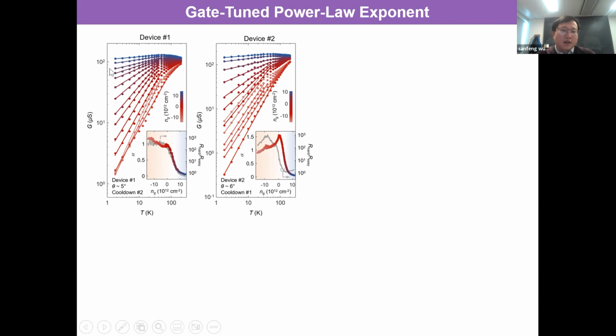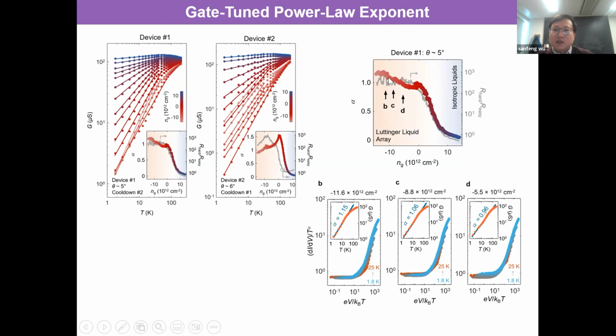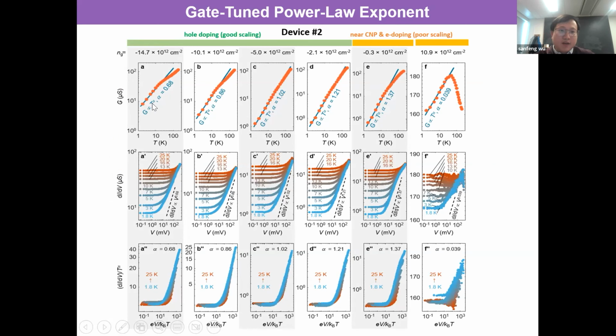We can also vary the density. These are plots of 2 devices with different densities. We can use a gate to change the doping. As long as you are on the hole side, you have very strong anisotropy and good power law scaling, as you can see here. I give you some examples in this device where we choose different gate voltages, and you see alpha can already be changed. So alpha can change from 1.15 to 0.96. This one is not too much, but the other device changes even more. This single exponent behavior also survives for different alphas over a wide range of doping and different samples. Here's another sample. You can see alpha can change from 0.7-ish to 1.2. So as long as you're on the hole side, we see good power law scaling down to, in this case, 1.8 Kelvin.